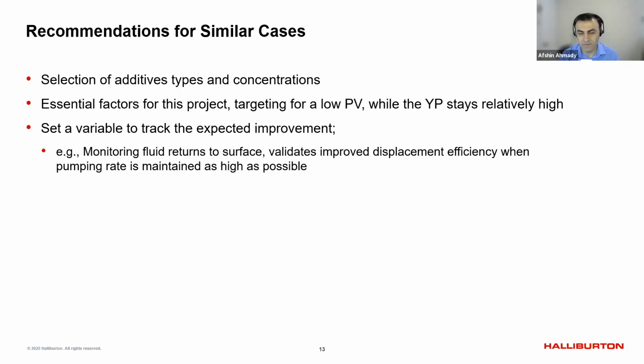And how you could just validate the improvement. For this project, I was talking about like displacement efficiency is getting better. Simulation is saying something, but actual job, it could be different because of tons of variables there. Just like, for example, if you don't have good centralization, the one Raf just covered in the previous session. We were monitoring the return. You could see more return of spacer or cement if you design the cement back to surface when you're pumping it at lower rate. By increasing to a faster or higher pumping rate or higher velocity, you could see the improvement. You get the expected volume of cement or spacer back to surface. That was the best indication.